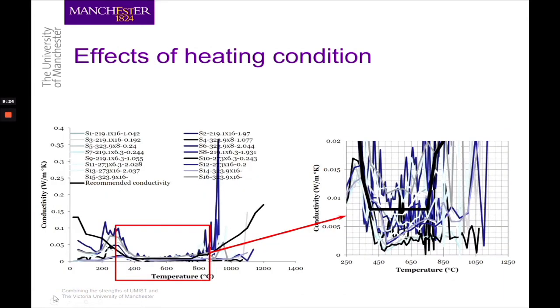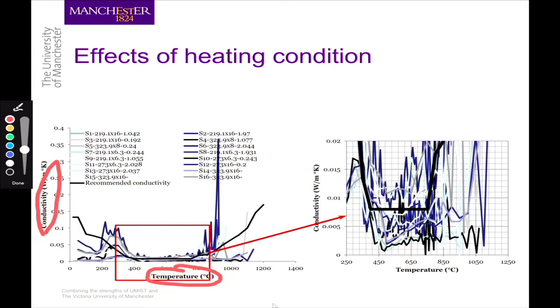Because it is by expansion of the coating, it's important to understand the expansion mechanism. And the expansion mechanism is not just temperature dependent, it's also dependent on the rate of heating. That's really important. So what we have done here is some fire tests, and we've plotted the temperature-time curve and the thermal conductivity-temperature relationship, based on the inverse calculation which I mentioned earlier, for the intumescent coating which we've tested.